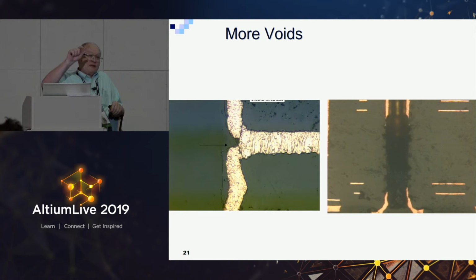Especially in the microvia, one of the problems we have is that it's so small, it can trap a very tiny air bubble. And that air bubble can sit at the bottom of the hole, and it prevents the solution, plating, and chemicals from getting to it. But an ever so small amount of metal does get to it. It'll pass all the electrical tests, but it will fail in the field. And what we're worried about is passing conventional electrical tests and then failing in the field, because that's under your warranty and under your company's name, not the fabricator's.